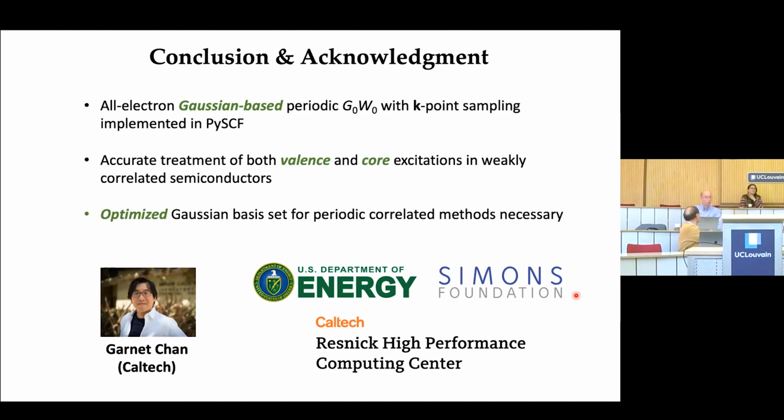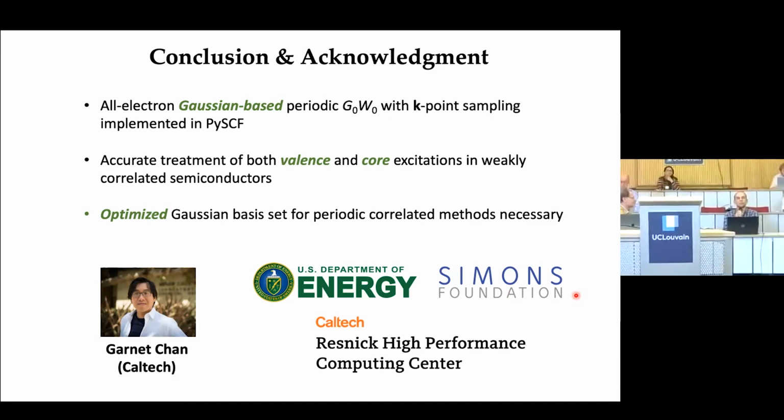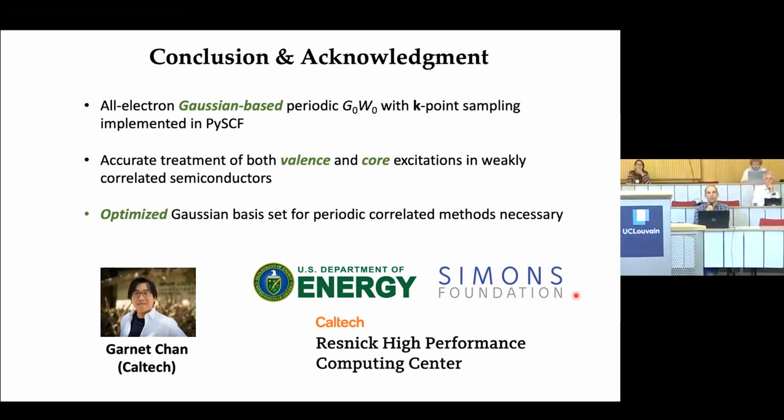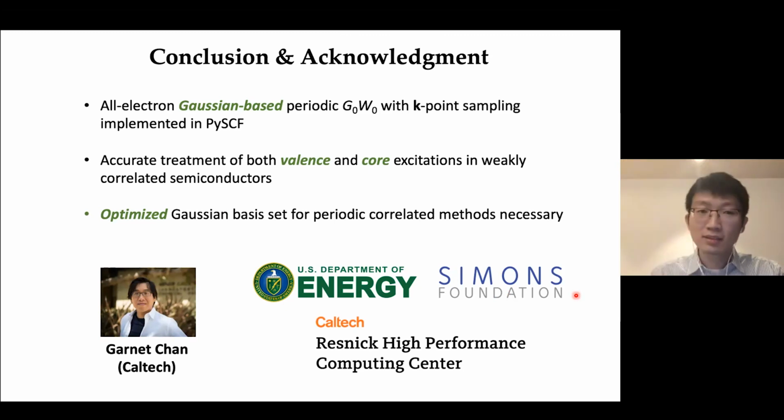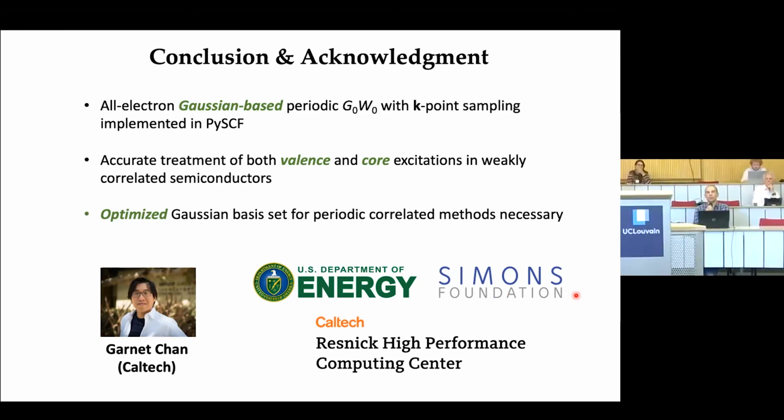Hello. Thank you very much for the nice presentation. I just would like to comment on the zinc oxide comparison you made. In your all-electron calculations, you completely neglect the relativistic effect. Whereas when we use pseudopotentials, implicitly, thanks to the pseudopotentials, we have some of the scalar relativistic effects that are included readily without even noticing it in the final results. So that may explain why you still have, let's say, 0.2 difference for zinc oxide compared to the other plane waves evaluations.